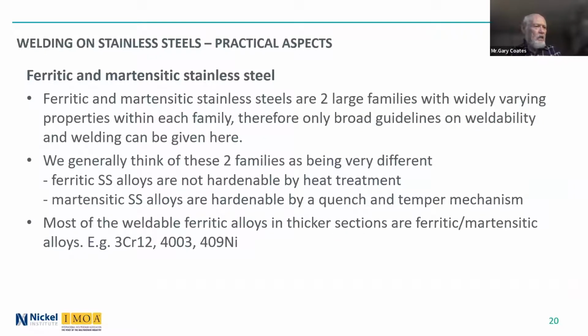In the time remaining, I want to move on to the ferritic and martensitic families. These are two families that have a great number of different alloys in them with varying properties, so we can only talk about broad guidelines here on weldability and welding. We think of these two families as being very different. The ferritic stainless steels are not hardenable by heat treatment, whereas the martensitic stainless steels are hardenable by a quench and temper mechanism.